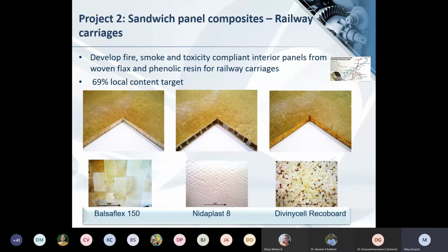And here, while in the early case we used the expensive Nomex core, we prepared the sandwich panels from, again, woven flax and phenolic resin. But the cores used were balsa core, which is a type of wood core, Nidaplast, which is a polypropylene core, and cardboard. So the processing technique was the same. Prepregs were formed, and then compression molded at the right temperature to form the panels.